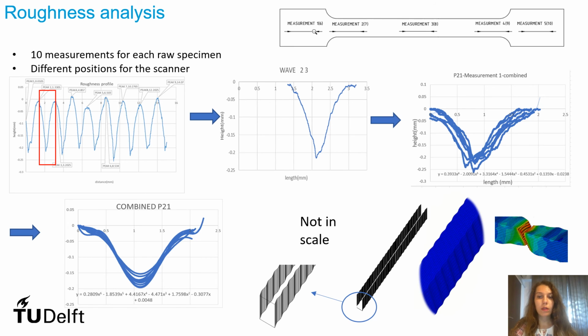Furthermore, all these calculations were put together to extract a 6-degree polynomial that best describes the roughness for one type of specimen. As you can see, the roughness is really small, it's just 0.2 millimeters on one side of the specimen, and the length of the measurement is 2 millimeters. This is almost close to nothing.